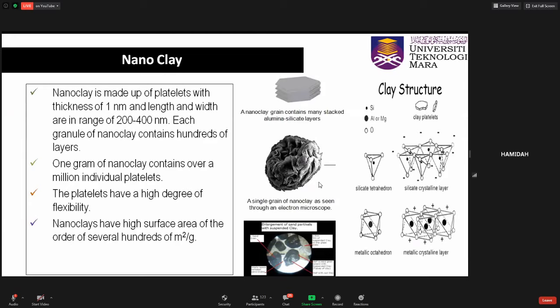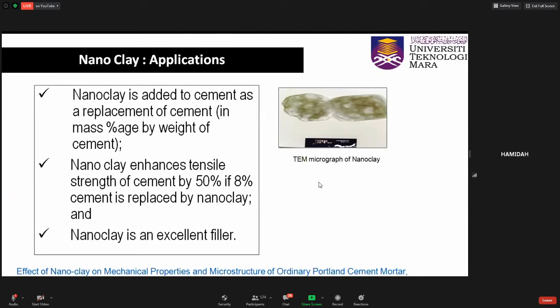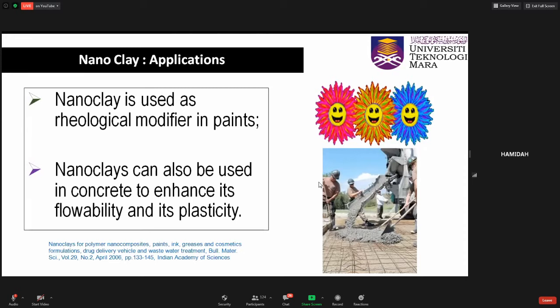Nanoclay is made up of platelets with thickness of 1 nanometer and length and width in range of 200 to 400 nanometers. Each granule of nanoclay contains hundreds of layers. 1 gram of nanoclay contains over 1 million individual platelets. Nanoclay is added to concrete as a replacement of cement material. It was found that tensile strength of concrete increased by 50% if 8% cement is replaced by nanoclay. Nanoclay is also used as a rheological modifier in paints and increases flowability and plasticity if added into concrete mix.